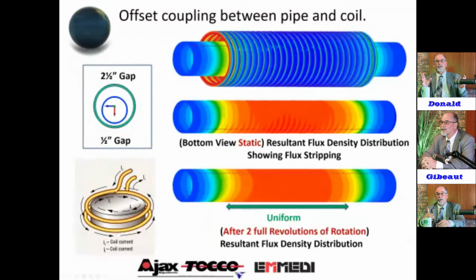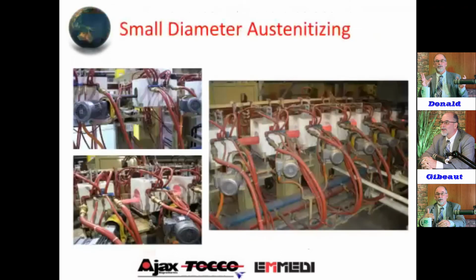If you stop that line, you'll see stripes on the bottom where it's overheated, like this thermal rendition here on the pipe. But if you have 2 full revolutions of rotation within a given coil, you get that condition right down here at the bottom where it uniformly heats, that efficiency offset. So what that allows us to do, even though that's uncomfortable to look at, is a broader mix for a given coil design to run in the coils.